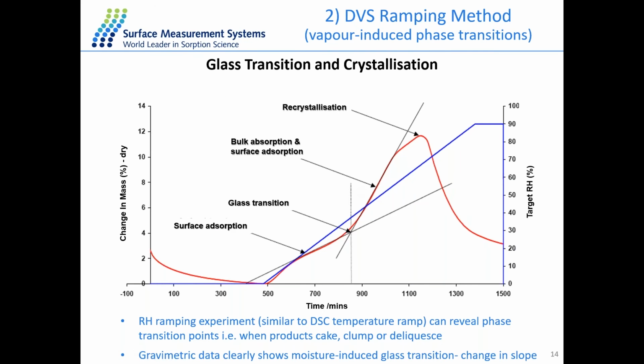The other method I would like to introduce here is the ramping method, which is a much quicker and easier way to study the stability of the solid material. And it's very similar to the DSC temperature ramp. So in case of DVS, we ramp the humidity from 0 to 90% RH at a constant rate. And here's the result for the lactose sample.